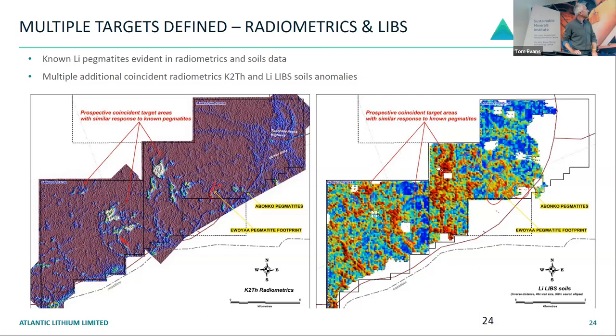But back to the LIBS here. We've tried to understand what these levels are. The blues would probably be around 0 to 100 ppm in soils through the LIBS. And then the greens around that 100 or 150 to 300 ppm. And then when you're on the pegmatites here, you're between 300 to 600, 700 ppm in soils. But this particular feature here, the Afrangwa granitoid and the Ekrabadzi granitoid here, they're sitting around 1500 up to 9000 ppm in soils. We've assayed rock chips, but we don't repeat those values.